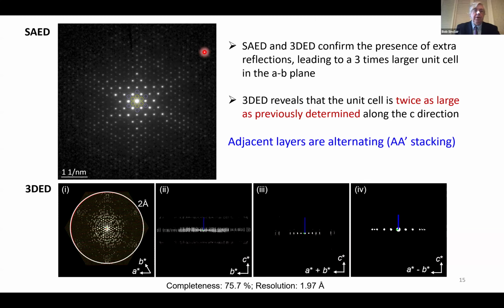I'm curious about the effects of defects. With the imaging, of course, you can see defects like grain boundaries or stacking faults and so on. But if you're not doing that direct imaging and you're relying on summations to form a better crystal structure model, what effect do the defects, which you may or may not know are there, have on the summations when you try and improve the data for atomic structure of crystalline materials?